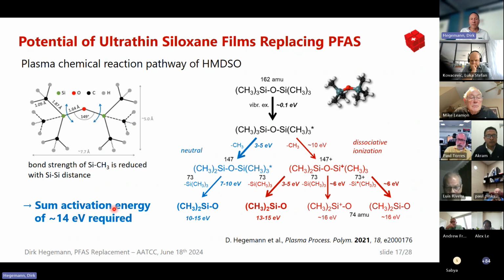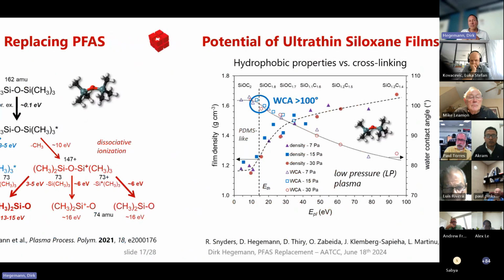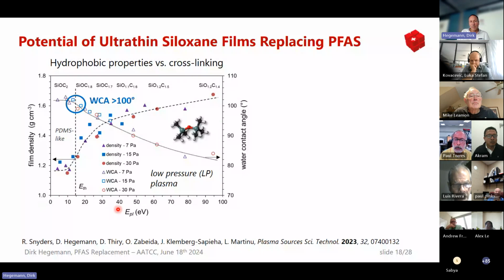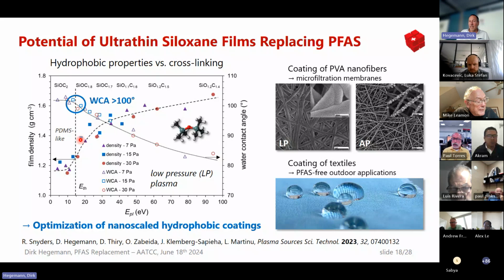In this example, it's around 14 eV, and this is a key parameter because now you can use this energy and apply it in a controlled way to your plasma process, plotted here on the scale. Then you can, for example, measure the water contact angle, so the water repellent properties, and the density, and density tells you something about cross-linking. When you supply energy just a little bit above this 14 eV, you still have very good water repellent properties, but now you can already increase density, that means cross-linking, and you get very high durability.